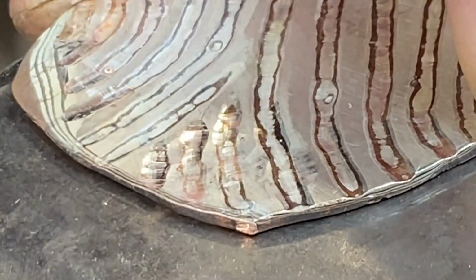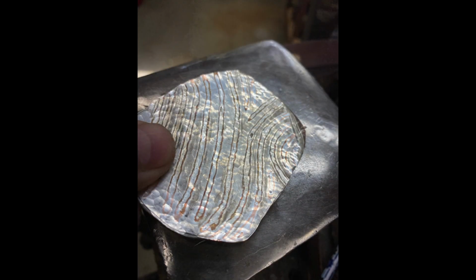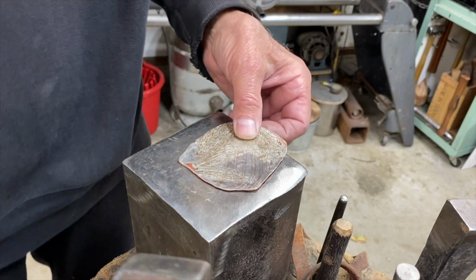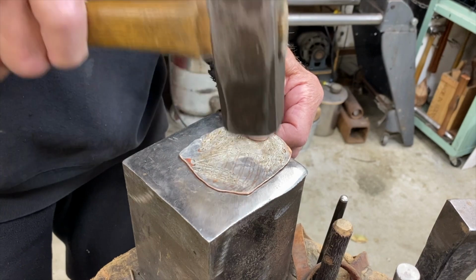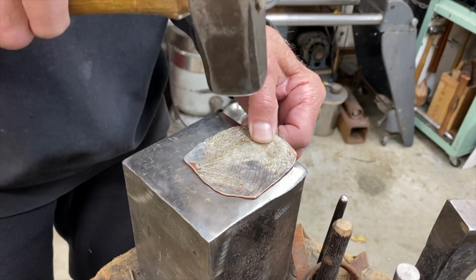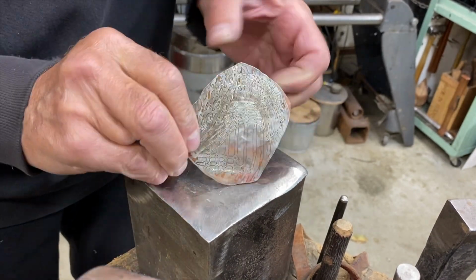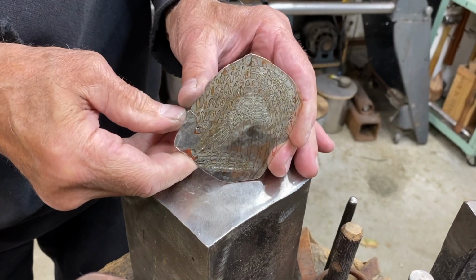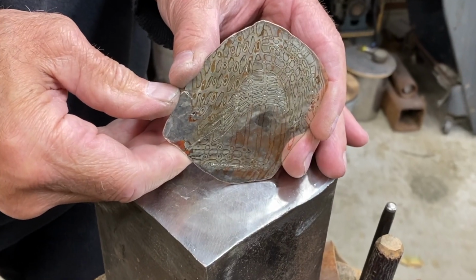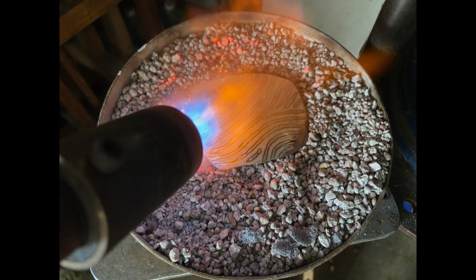Now you can see the metal rising up in the channels. I watch for this in the reflected light. The last step is to smooth out those rounded hammer marks with a flat-faced hammer, like in this clip from a later forging. Notice that I'm forging very lightly. I anneal the piece, then pickle.